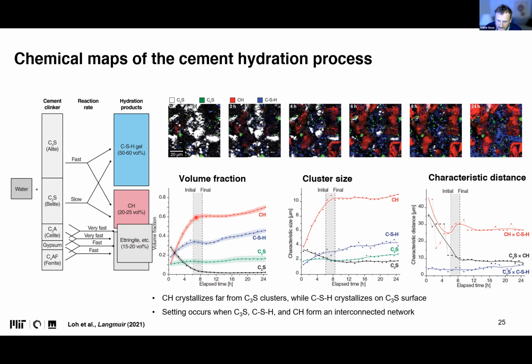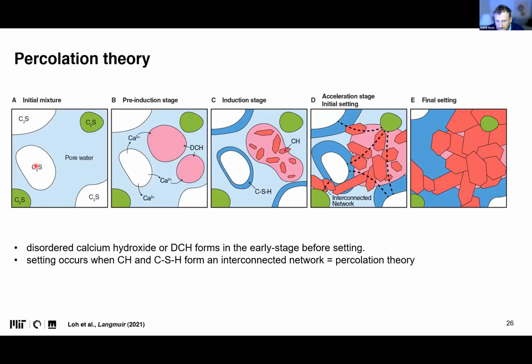And what we found out is that calcium hydroxide crystallizes far from C3S alite clusters, which is to be expected, and CSH crystallizes on the surface of alite. Setting occurs when C3S, CSH, and CH calcium hydroxide form an interconnected network, which is really obvious from these data. And this is the model we were able to outline. What is quite new and cool is that the calcium, once created through hydration of alite, moves into pores as a disordered calcium hydroxide, and then crystallizes, and this grows with time, and when everything is connected, we get setting.